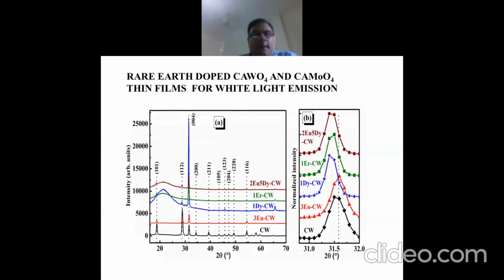We have also prepared their thin films, because if you want to miniaturize a device, thin films are better materials. So the best technique to prepare their stoichiometric compositions is pulsed laser deposition, where we use a pellet as a target. The pellet is doped calcium tungstate or calcium molybdate, and we bombard this target with excimer laser pulses.